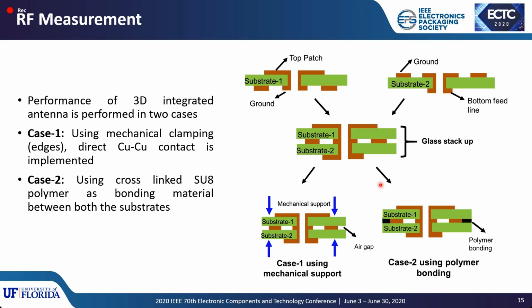In case 2, we used cross-linked SU8 polymer as a bonding material for both the substrates, and in this case the SU8 is completely cross-linked using a photolithographic technique.